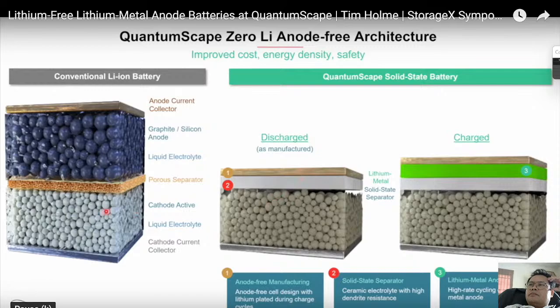The cathode is relatively similar. Both the active materials and ion conductors or catholyte inside the cathode share a lot in common with lithium-ion batteries, but we've replaced the anode with nothing in the manufactured state. And then all the lithium that's in the cathode material as manufactured will, on the first charge, come and plate at this interface between the separator and the current collector and form this block of lithium metal at the anode side. And then this is the lithium that cycles back and forth as you charge and discharge the cell.